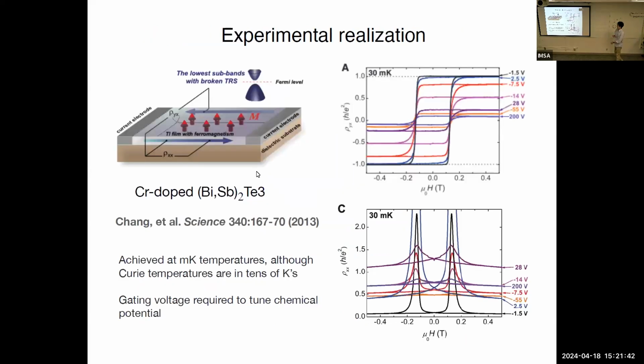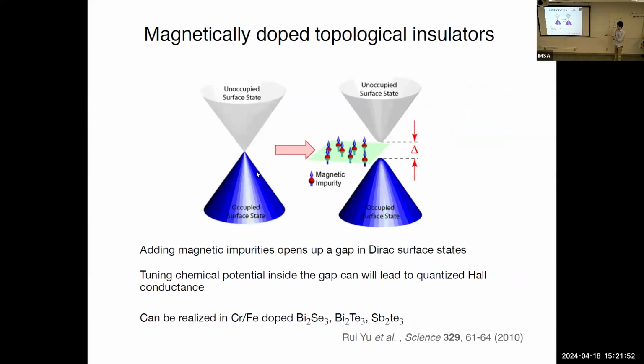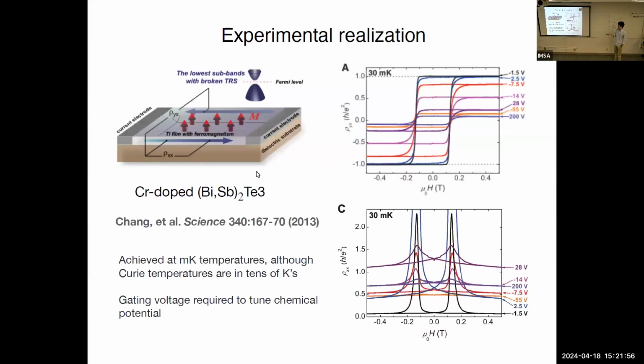And it took about 3 years to realize it in real materials. It was actually realized in chromium doped bismuth antimony telluride. And here we show the Hall conductance, the hysteresis loop of Hall conductance as a function of applied magnetic field. As you can see, you can observe full quantization even with just going to 0.2 Tesla, which is an incredible improvement compared to 5 Tesla or 20 Tesla. But one caveat is that these are all done at very low temperatures, 30 millikelvin, which makes it practically not really accessible.